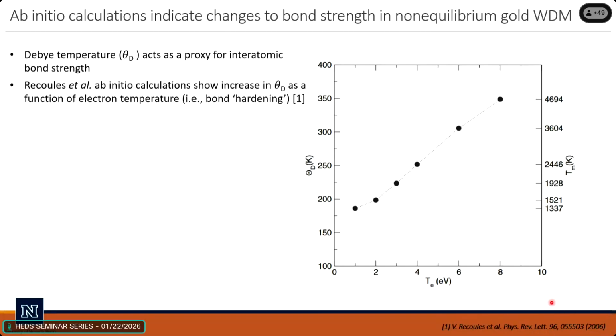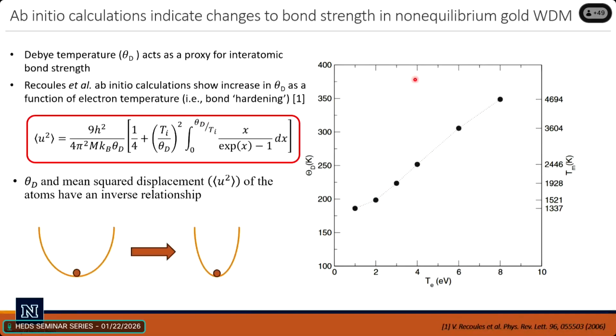Starting with Vanina Recoules in 2006, she wrote this paper where she said, here is the bond strength, which we parameterize by the Debye temperature. So the higher the Debye temperature, the stronger the bonds. And she said, as the electron temperature goes up, the bond strength goes up. So it's kind of counterintuitive. You take a material, you whack a laser into it, the electrons get really hot, and the material gets stronger for a brief amount of time, right? So there is an inverse relationship. Don't look too carefully at this massive equation, but the mean square displacement of the atoms, how far they're vibrating around, is inversely proportional to the Debye temperature. So as I make the Debye temperature go up, the atoms get more strongly bound. So that is what we're seeing here.